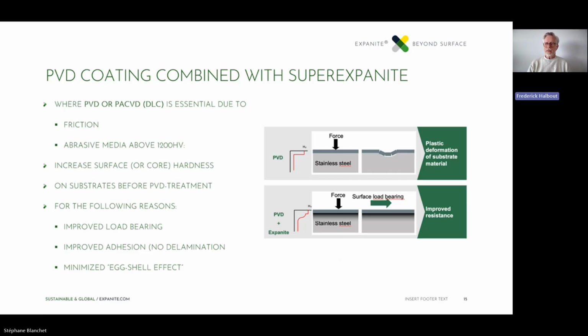So then why do you need an Expedite? If you have this high hardness in the PVD coating, why do you need to do an Expedite treatment on the part before you do the PVD? Well, stainless steel, especially austenitic stainless steel, is very soft, and it's actually way softer than is recommended for any PVD to be put directly on the surface. It can be done, but especially when there is a case of plastic deformation, such as in this application that Stefan told you about, where there's a high velocity, there may be movement that is bigger in the material than is allowed for the PVD, and then you can have an eggshell effect, such as in the picture on top.